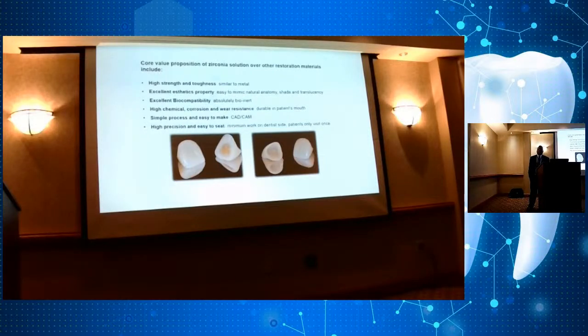Just a question, because we're talking about it. E.max, I'll just use the brand name. I mean, 850 is the sintering temperature for that. So if you have a finished crown and a tapered margin, 1,000 degrees seems it would deform that. Yeah, I take it back because you can go up to that temperature, but hold it in air for 5 minutes. At the highest, prosthetic ceramic has a higher melting point. So you would actually take it just below the glaze temperature, whatever glaze you're using. And just by protocols of the manufacturer, let's just say lithium disilicate is at 850 or something like that. Go below that a little bit, maybe 25 degrees.